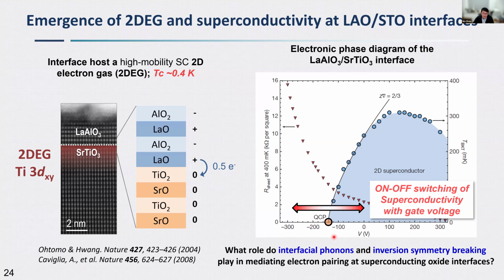In this system, the superconductivity can be switched on and off just by gating to tune the charge carrier density. But our collaborators found that you can also tune the carrier concentration by changing the lanthanum aluminum ratio in the LAO layer. So we'll get back to that. We want to see how in this particular system the 2D electron gas would induce new interfacial phonon modes, and how this correlates with inversion symmetry breaking, and also, more importantly, the emergence of superconductivity in this insulating